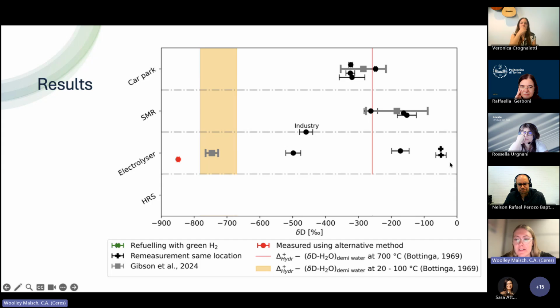I'll walk you through these. When we saw this signature of around -50, we were so surprised that we went back again to measure the hydrogen again, and we got exactly the same source signature within error estimates of one another. And then we have one point over here, which is from a laboratory electrolyzer, and our calibration range maybe can't go as low as this. So this value might be a bit lower than it actually should be. It may fall in here, but we don't have the calibration cylinders to calibrate that properly. However, you can see this really large spread in the source signature, which we weren't expecting.